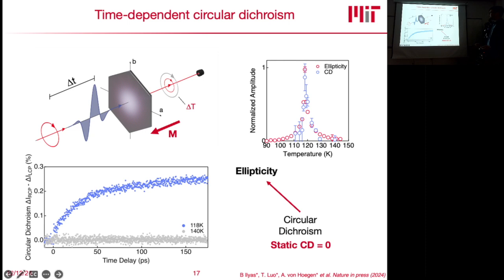One thing that can give you a circular dichroism in your material is breaking time reversal symmetry. And one thing that can do this is a magnetization, an out-of-plane magnetization. This is very similar to what people usually do in a measurement on a ferromagnet, in this case, or on a ferrimagnet. So this strongly suggests that the ellipticity and the circular dichroism come from a transiently induced, long-lived magnetization in this otherwise fully compensated antiferromagnet.